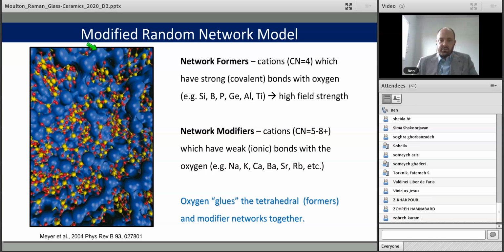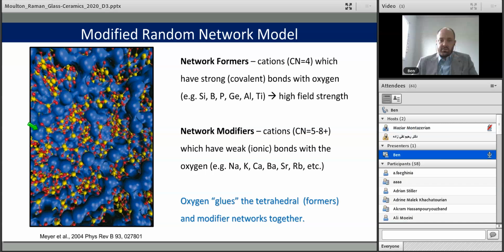That brings us to a sodium silicate network. These blue blobby features are an isosurface of electron density around the sodium. And in any liquid, these will be diffusing around. And so some people come to the belief that these sodium channels are constant within the network, and therefore they might be used for sodium migration, for instance, in conductive materials. But they're actually dynamic. They're diffusing around. At the same time, the yellow and red structures, which are the silicon tetrahedra, are also shifting around and diffusing.